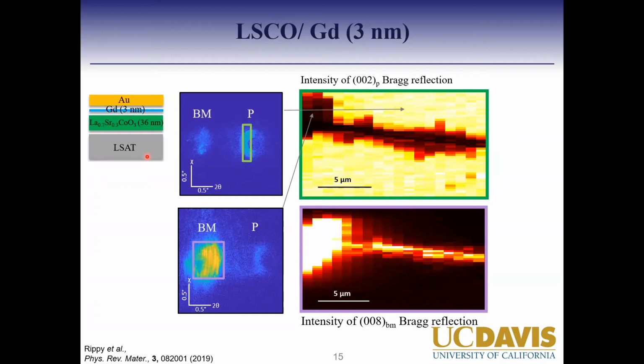Right. That's actually a very good question, and it's something we spent some time figuring out. We have quite a bit of control on the thickness. So 3 nanometer is pretty accurate, plus minus like 0.1, 0.2 nanometers. And we can measure that after we have grown these films using X-ray reflectivity. The surface roughness, on the other hand, when we grow thicker films, is pretty good.